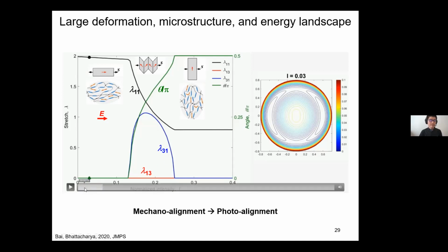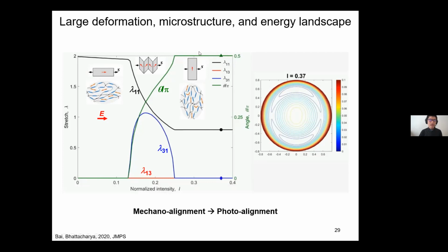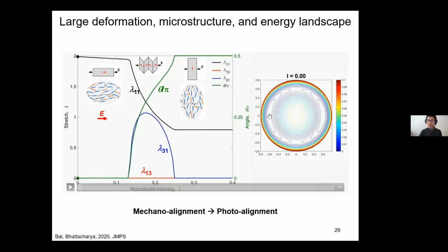So let's focus on this energy landscape. If I increase the light intensity, you see the energy landscape becomes different. And furthermore, after some time, my global minimum becomes here and here. So in the end, at a relatively large light intensity, these mesogens align perpendicular to the stress, to the polarization, right? If you track this angle, initially it's 0, increases and becomes pi over 2. It's very interesting from mechanical alignment, because initially it aligns with the mechanical stress, and becomes, as I call it, photo alignment, perpendicular to the polarization.